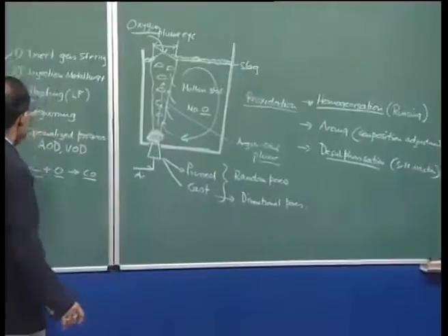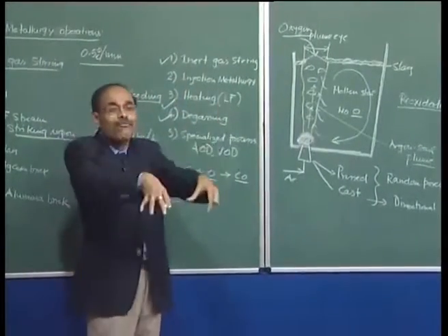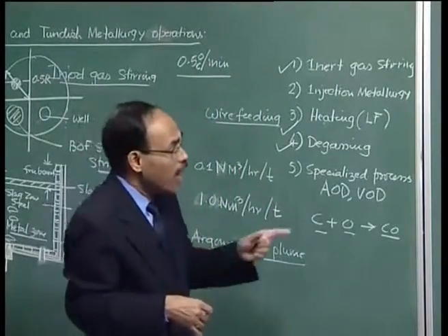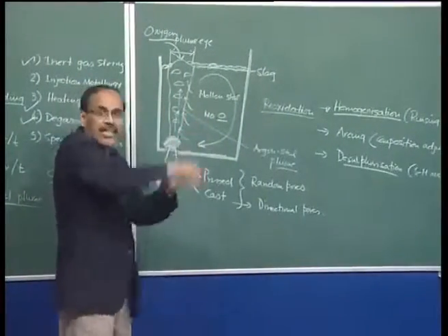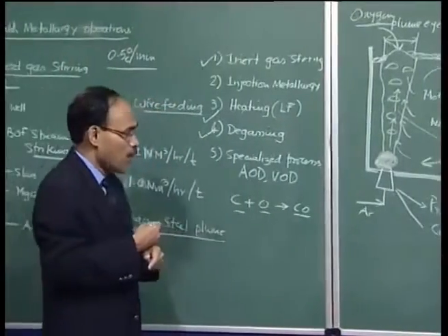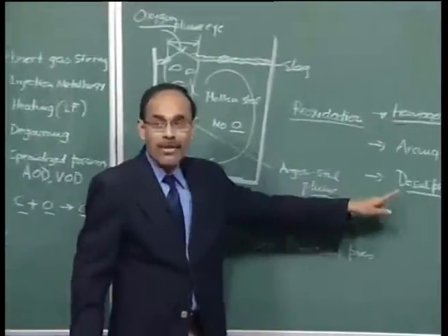Arcing, which is the heating operation, is when we add a lot of alloying additions which have to dissolve, so the flow rate is going to be a little bit higher. For desulfurization, we require extensive slag metal mixing in the system, which is carried out during the beginning of the argon rinsing operation, immediately following deoxidation, in which case the flow rate could be very, very high.